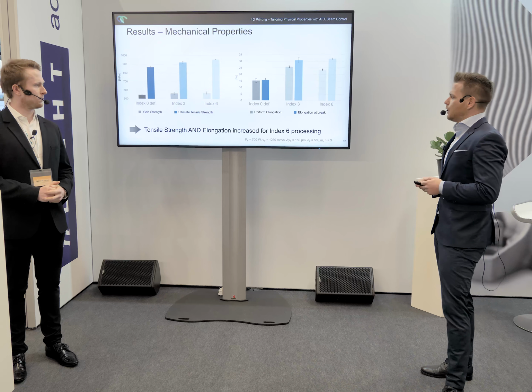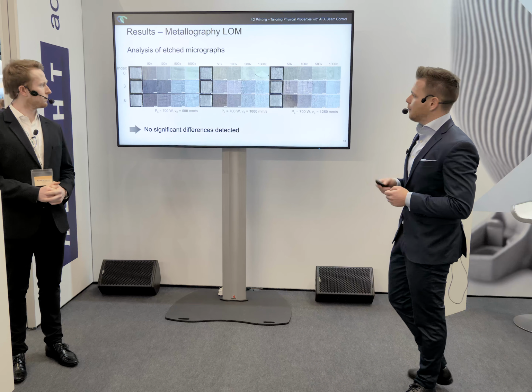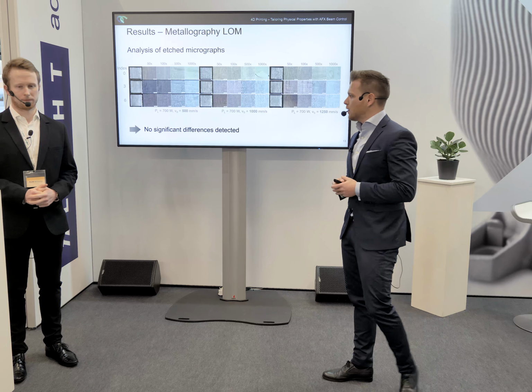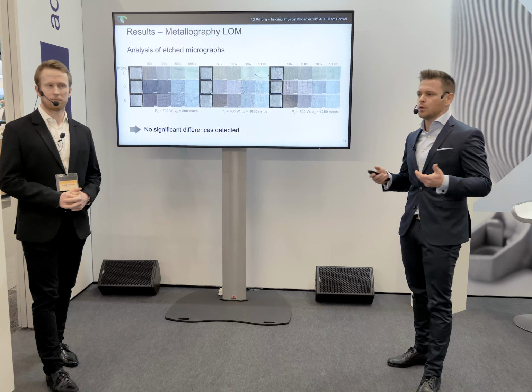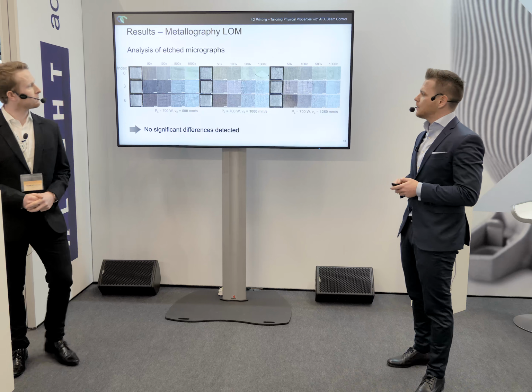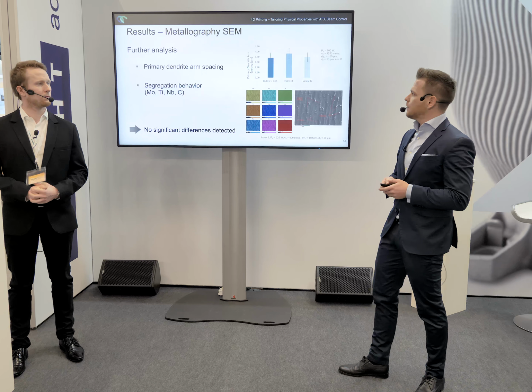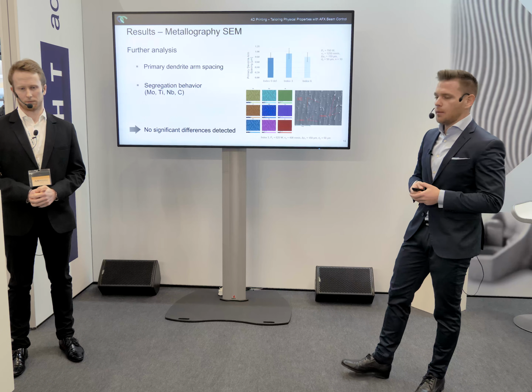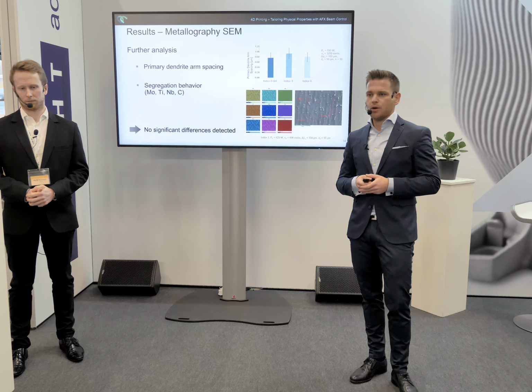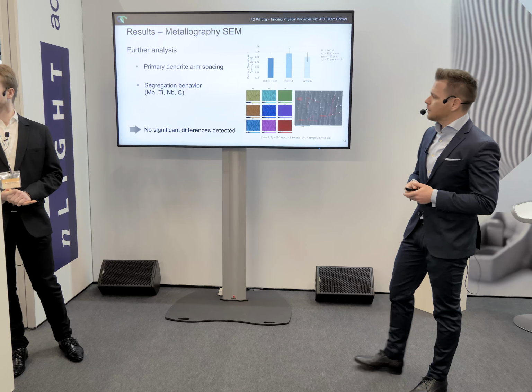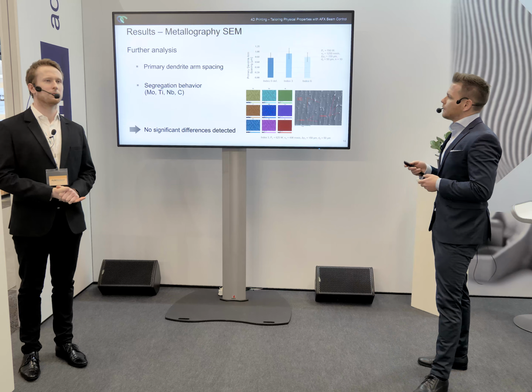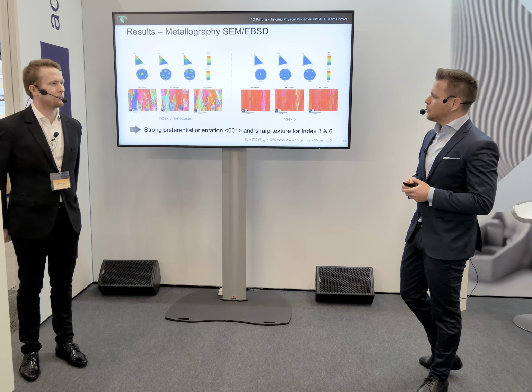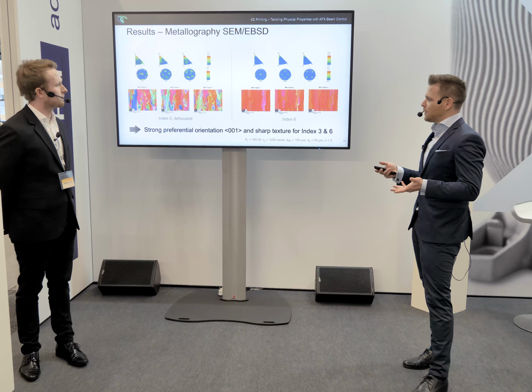Searching for the reason, we took a look at the metallography, especially at the edge cross sections, but there was no big difference between the indices, as well as in the further analysis via SEM in terms of primary dendrite arm spacing and EDX, the segregation behavior. But looking at the EBSD images showed the reason, so to say.